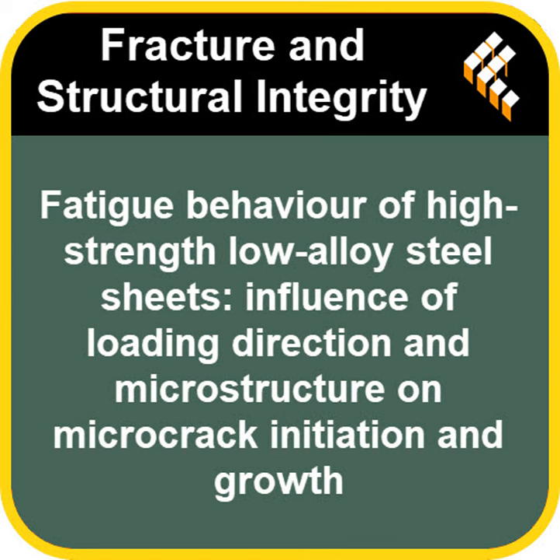Using hardness tests. Precisely. They did micro-hardness tests on the samples after the fatigue tests were done, and the results lined up perfectly. Hardness generally increased with more plastic strain, which you'd expect. But at that high 0.3% strain, the TD samples ended up the hardest, around 217 HV. Then came DD at 200 HV, and RD was lowest at 186 HV. So TD, DD, RD in hardness. Yep, and that hierarchy perfectly matches the changes they saw in the N prime exponent. It confirms those internal structural changes were making the material physically harder, especially in the TD direction at high strains.